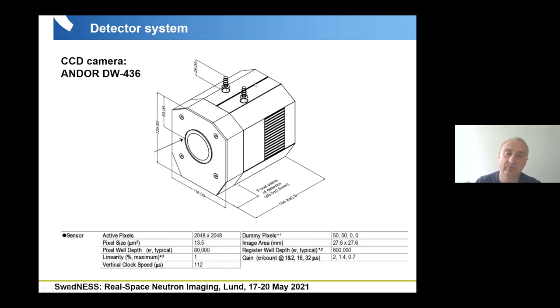So it is quite a bulky device, and it is very sensitive to light. Here you can count even single photons. And we need this because the efficiency of the scintillators and the neutron flux which we have are not very high. So finally, you are fighting with quite a lot of statistical noise and also reduced efficiency of the scintillator. So finally, you need really very sensitive detectors, which are unfortunately very expensive.